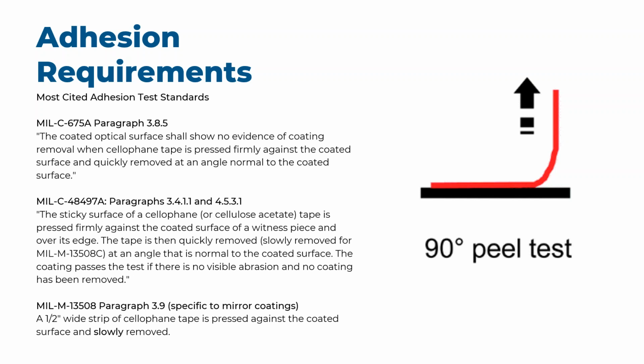So the way that we understand this is you go towards the middle of the substrate, you tightly adhere the cellophane tape, and you pull away aggressively. That is really how you should test adhesion. But again, depending on how you're testing or your customer requirement, it could be a little different. You'll see in MIL-M-13508, paragraph 3.9, because this is a mirror coating, which are typically softer than other dielectric applied coatings, the pull away is a little slower. And then you have the subjectivity of how fast is a fast pull, how slow is a slow pull.